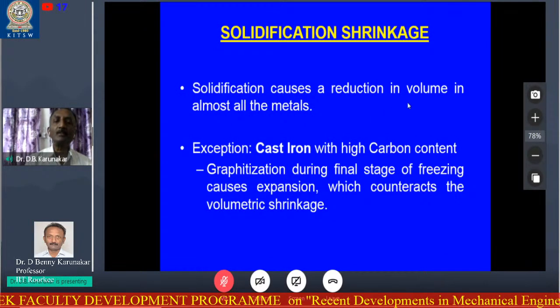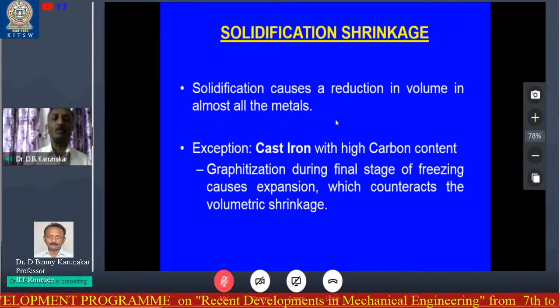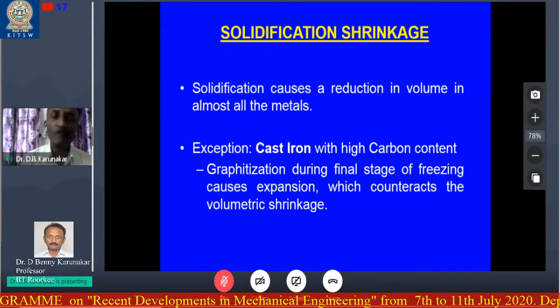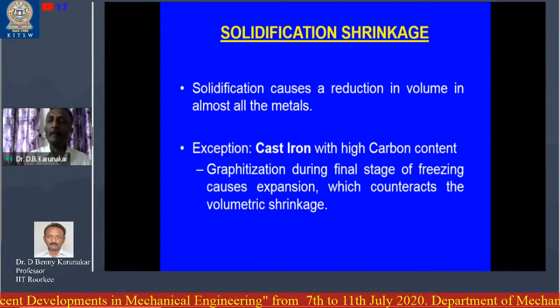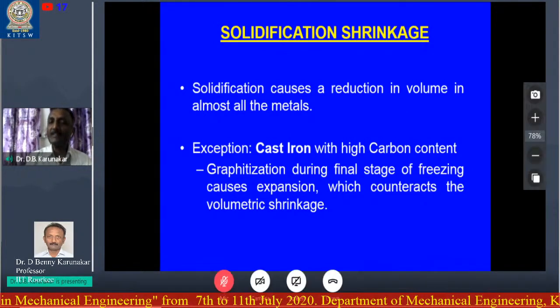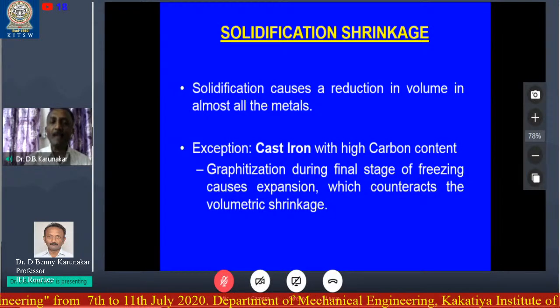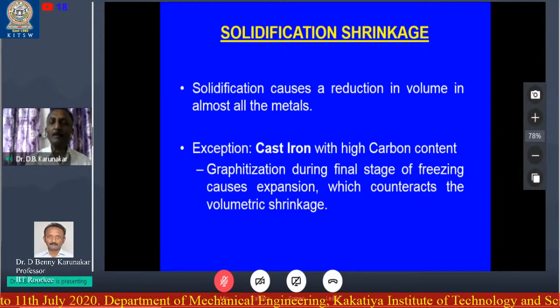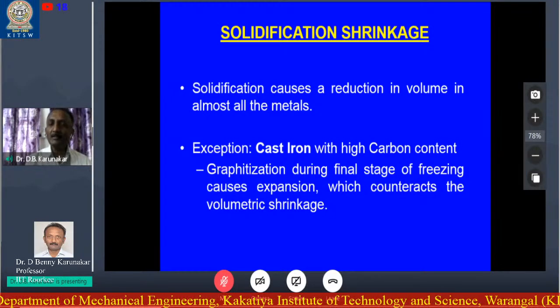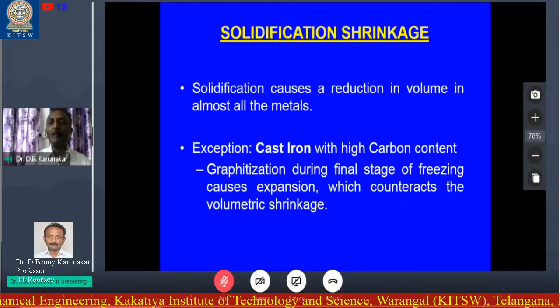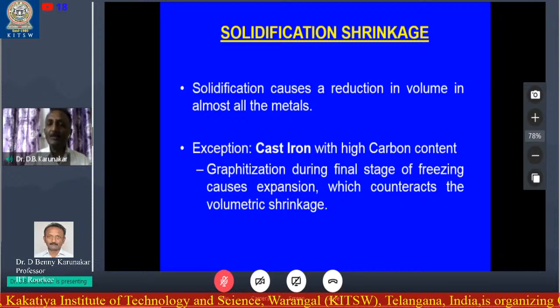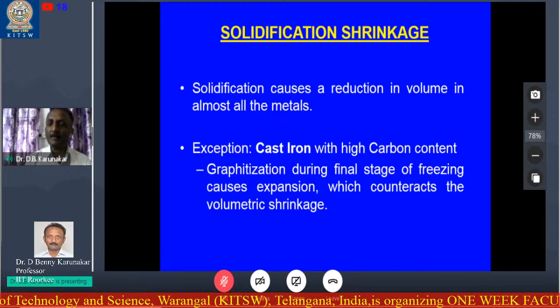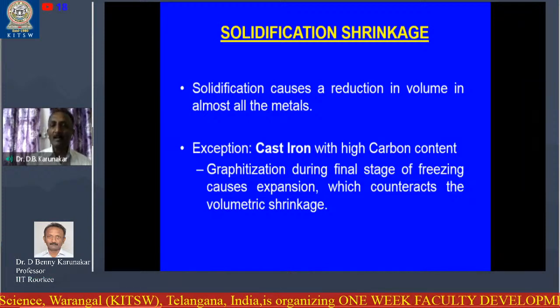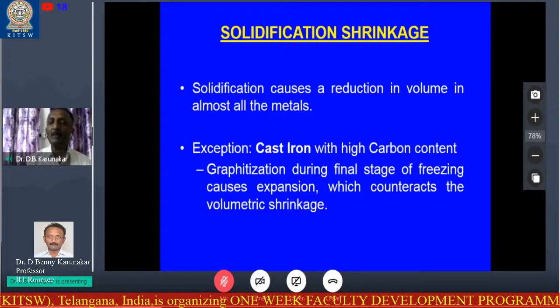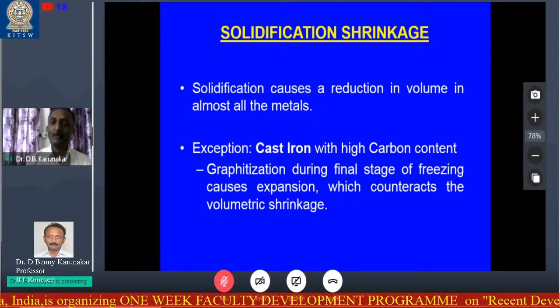Solidification causes a reduction in the volume in almost all the metals. So every metal undergoes shrinkage except cast iron. In cast iron, what will happen? The carbon in the cast iron is in the form of graphite. So graphitization takes place. Because of that, there will be bulging and the volume will be increasing during solidification.